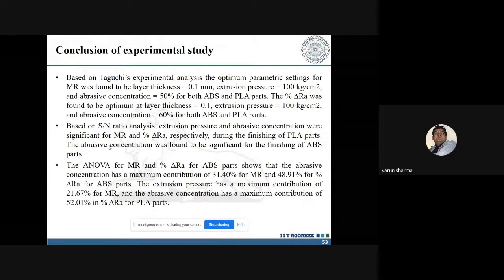Now, the percentage improvement that we were having, for example, for relatively softer material, we were able to improve the surface finish by 52%. Whereas for ABS, we were able to improve the surface finish by 31% as compared to the initial. Now, if you give me a 0.1 layer thickness of the additively manufactured part, I may use over here a different set of the mesh size or the different kind of the abrasive media to finish that particular workpiece.